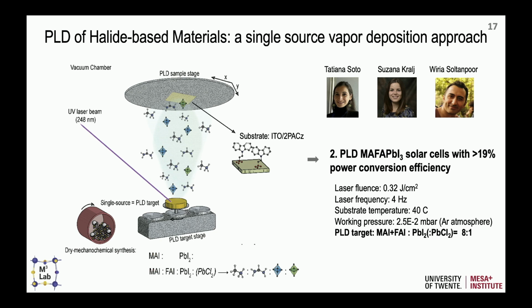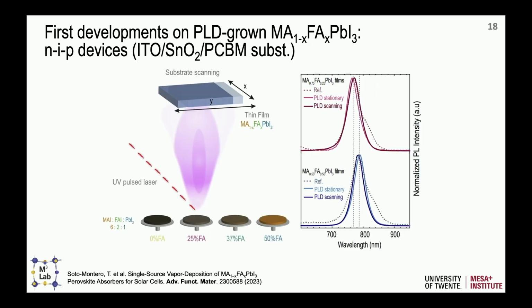I think in terms of what to say here is that because we work with these organic materials, and they are very highly volatile, we actually include a lot of organics in the target. So the target is not stoichiometric, we just make an atmosphere of organic materials when we do the ablation. So I already showed you how we make the target. So we basically take the precursors, mix them in a target, and use a laser. And in this case, we have different amounts of FA. And we also already heard from Juliane that FA is actually a very difficult material to evaporate. So that was also a very good test in our experiments.